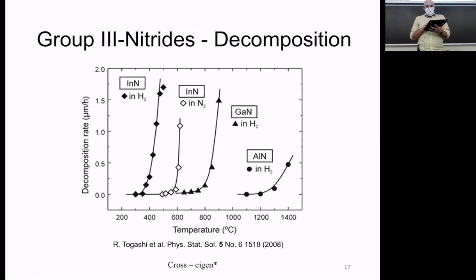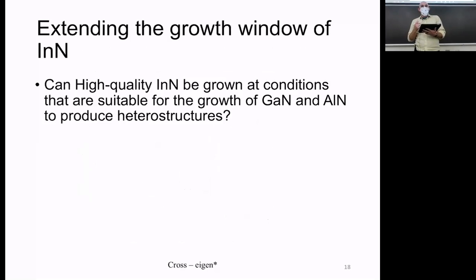This paper was published in 2008, and they were still dealing with this issue. So until recently, as in 2015 probably, this material wasn't grown above 600, 650 degrees Celsius, which is a big problem if you're trying to mix it with aluminum nitride and gallium nitride that are grown at 1,100 or 1,200 degrees Celsius. So that was one of the problems that I was working with. Can high-quality indium nitride be grown in conditions that are suitable for gallium nitride to produce heterostructures or to produce alloys? So a heterostructure is when I layer 2 different materials, such as gallium nitride, and then I put a layer of indium nitride on top of it. Alloys would be mixing gallium nitride and indium nitride in the same material to make gallium indium nitride together.